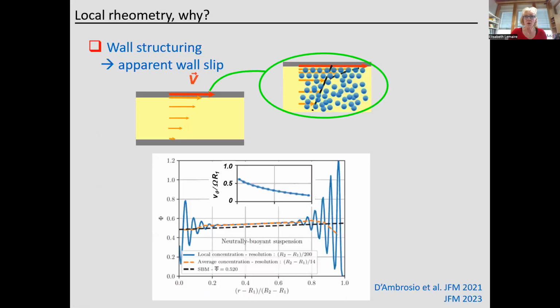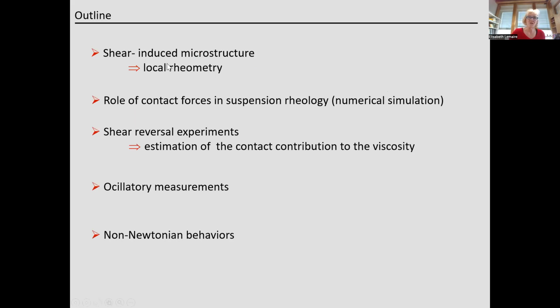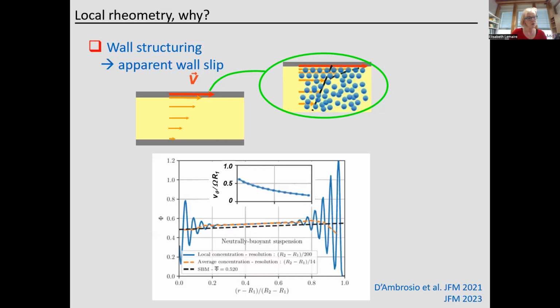Okay, so the first point is that the flow controls the microstructure in a suspension. So it's important to know this microstructure, and to know this microstructure, it's important to perform local rheometry experiments. Not always, because it's not so easy to do local rheometry, but it's important to refer to local rheometry measurements in order to know if the rheometric measurements we make are valid or not.